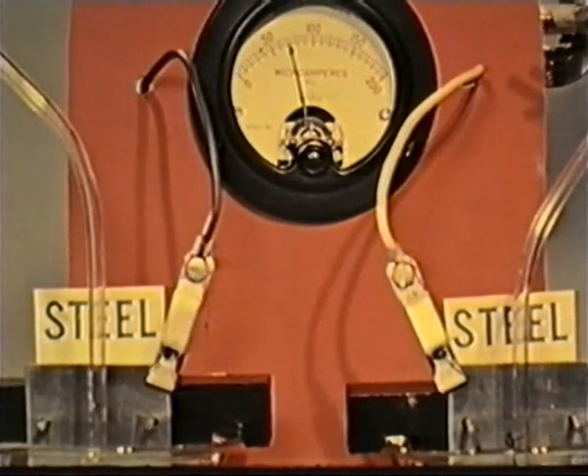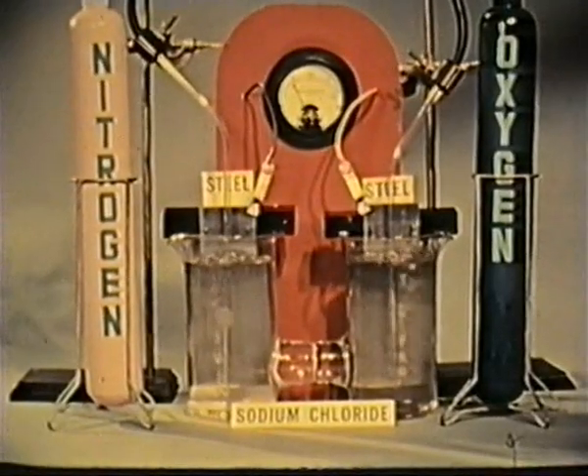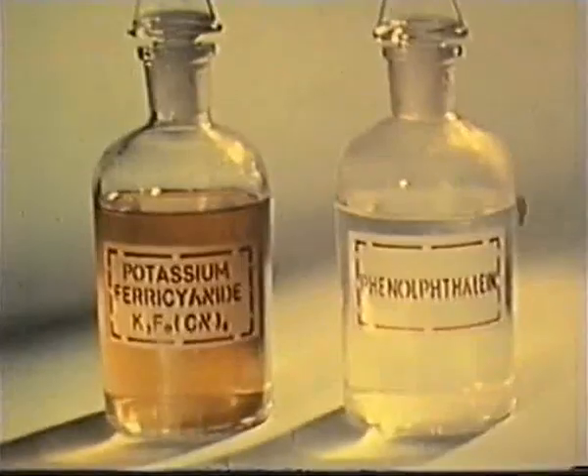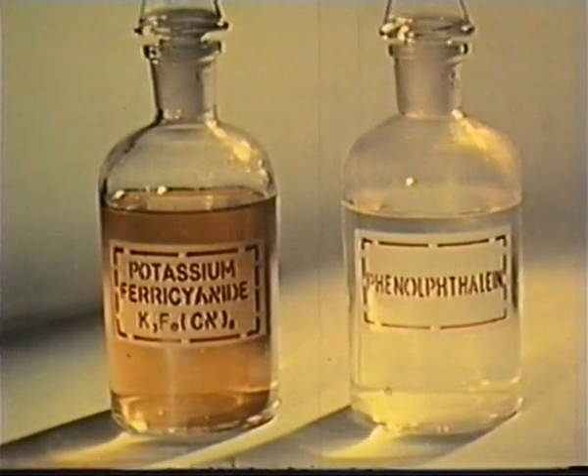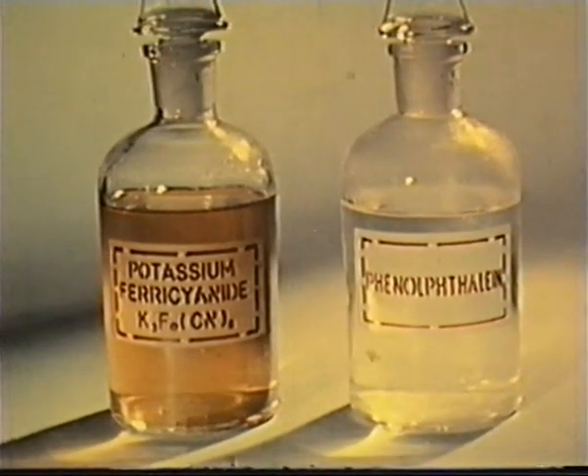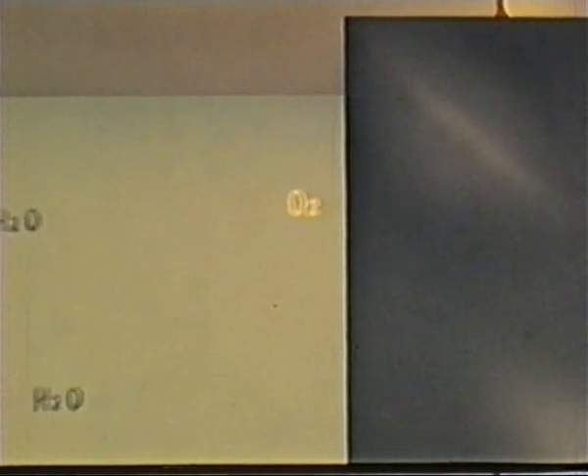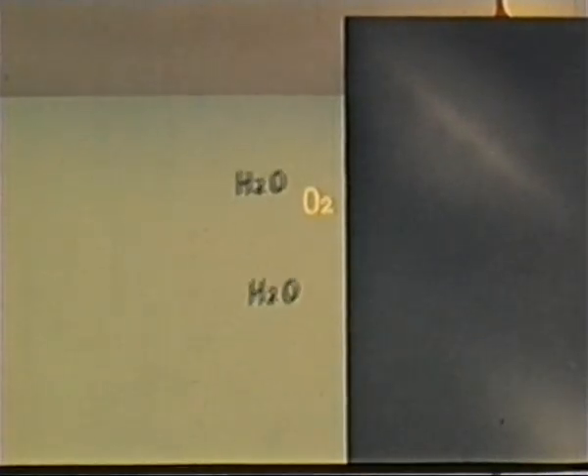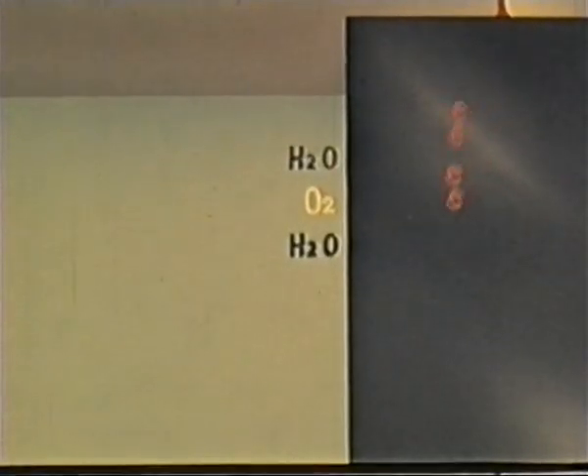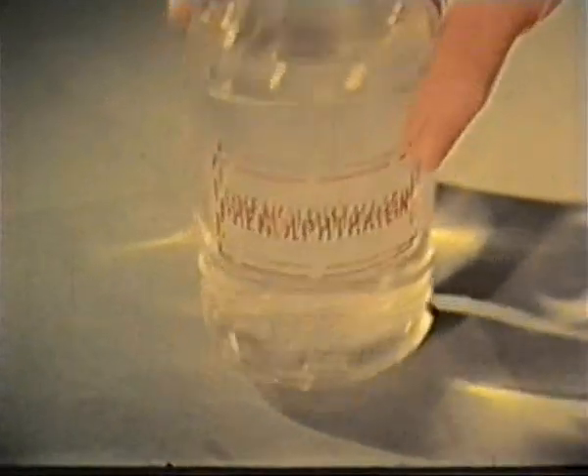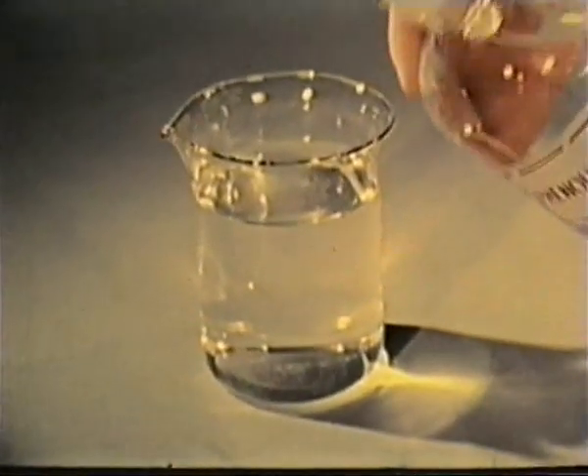Similar corrosion currents can be generated by differences in metal ion concentrations. The existence and location of anodes and cathodes in an oxygen concentration corrosion cell on a steel surface can be demonstrated by the changes in color of certain reagents as well as by the use of electrical instruments as in the preceding experiment. We have shown that the cathode reaction produces an increase in the concentration of hydroxyl ions as a result of removal of hydrogen ions or the reduction of oxygen.